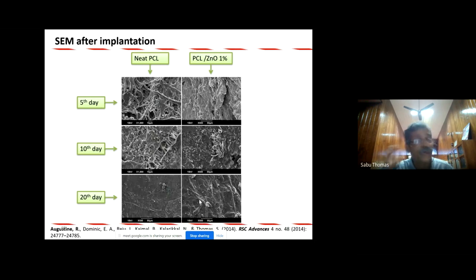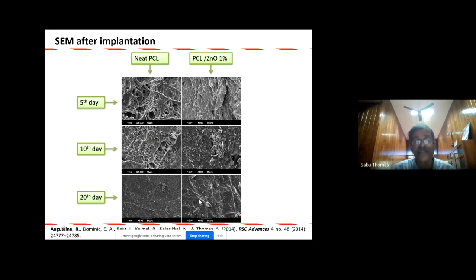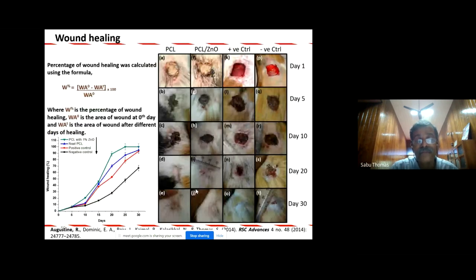Another important point I want to tell you, I already spoke. When you put a little bit of nanoparticles, the in vitro degradation of the scaffold becomes faster. You can see this is neat PCL. 5th day, 10th day, and 20th day. This is PCL with 1% of zinc oxide. Look at the degradation of the scaffold becomes much faster when you have zinc oxide.